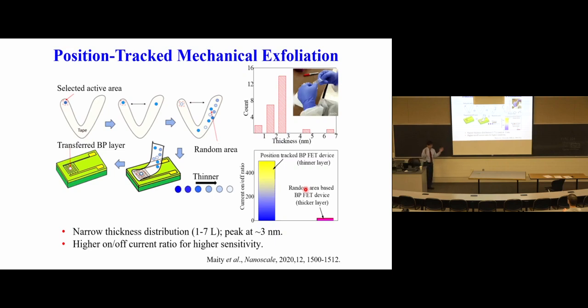With those learnings in mind, we looked at how we can better engineer the same BP sheets to achieve better sensing performance. So we improved this mechanical exfoliation process by tracking them, a simple position tracking. You could really achieve more uniform thicknesses. It's not monodispersed, but somewhere between 1 and 7 layers, around 3 nanometers in mode thickness. With those type of nanosheets, you can have a much higher on-off current ratio, which is indicative of